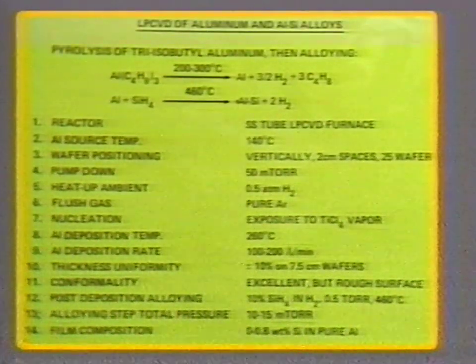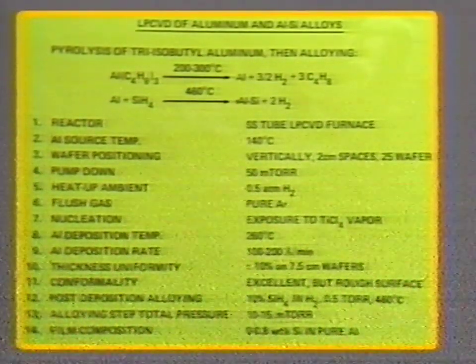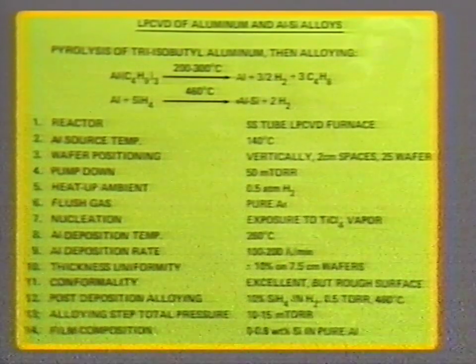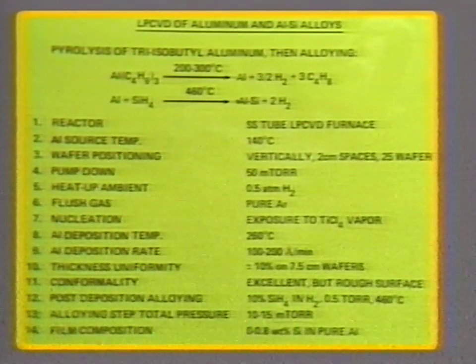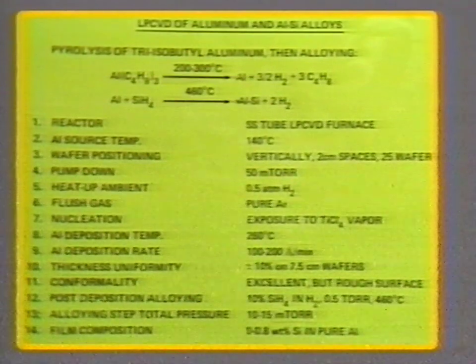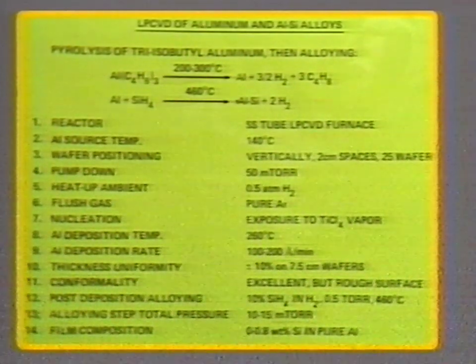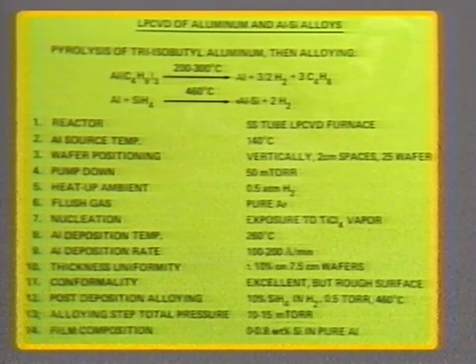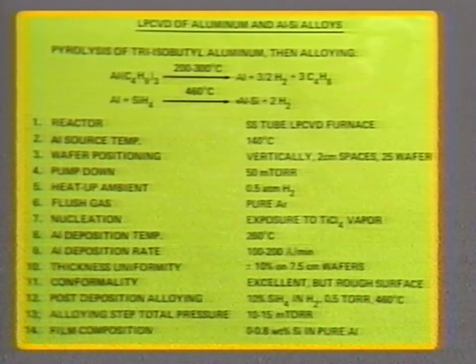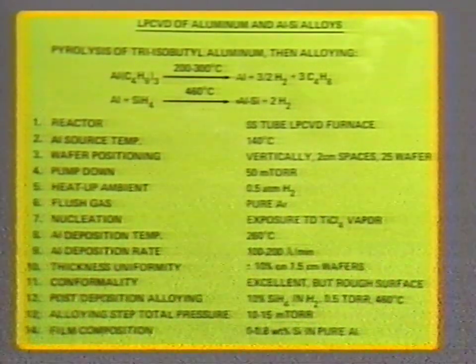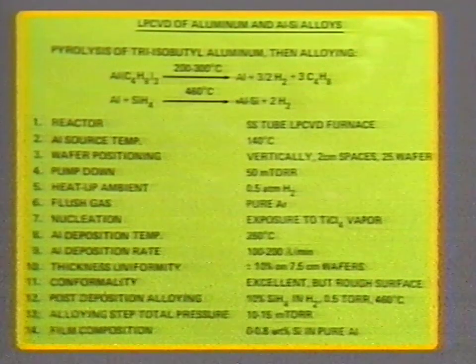This reference goes back to Cook from Solid State Technology, but it's a good example of what the reaction in principle at least looks like. The aluminum source temperature is 140 degrees C to produce enough vapor that can be introduced into the system to produce the aluminum reaction.